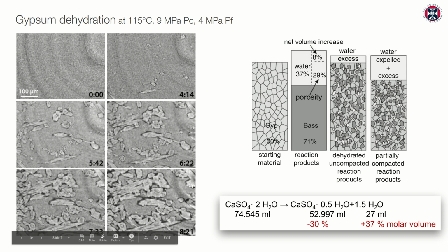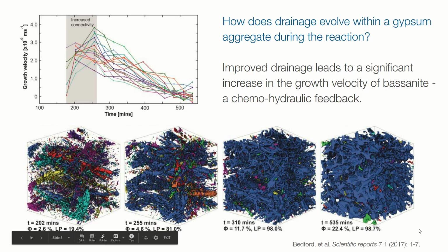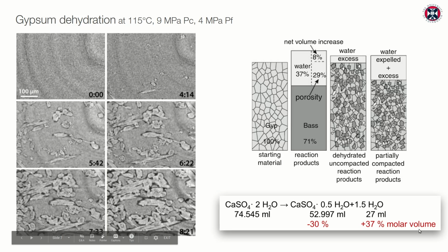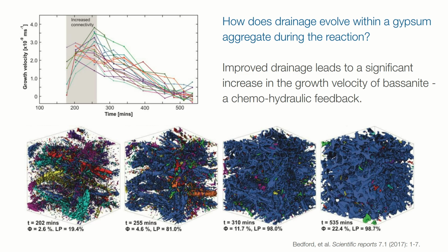That reaction goes along with a significant reduction in the solid molar volume, which is expressed here as these pores that form around the hemihydrate grains. But it also goes along with the release of a lot of water, and you see that there's a difference in the volume between these two, so that leads to pore fluid overpressure, which in tectonics has been considered to be a pretty important ingredient.